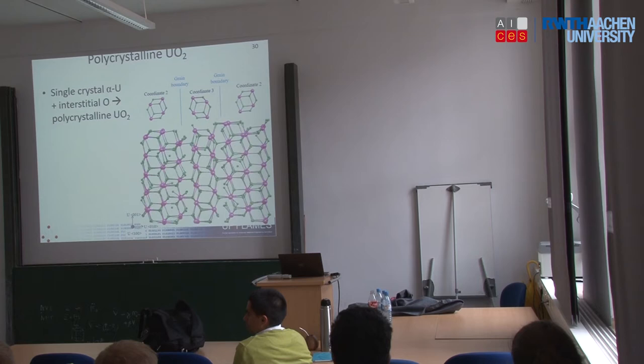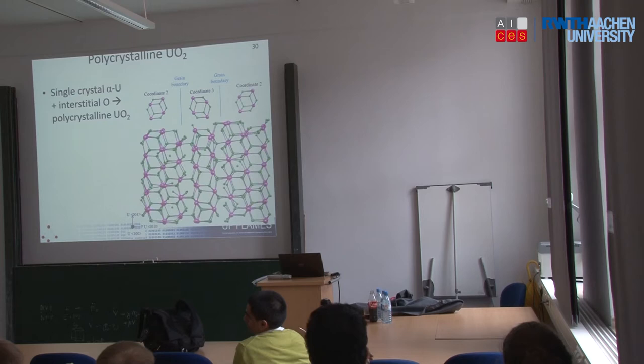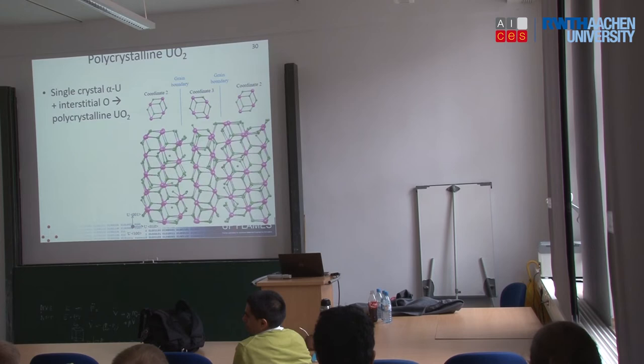But there is no universal potential, no universal set of parameters. They don't exist. Now, with DFT, you can pretty much take almost any material, put it into a DFT calculation, and get something reasonably sensible out of it. There are some well-known pathologies, and you have to do some tricks for different systems, but you can take VASP and you personally don't have to develop anything new for almost any system you're likely to be interested in. It's probably in VASP already. In this case, for empirical potentials, you have to develop them one at a time for the system you're interested in. That's one of the weaknesses.